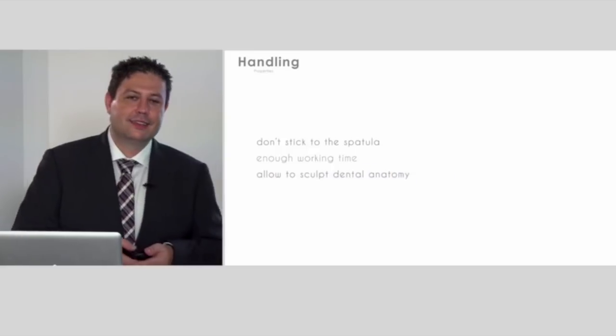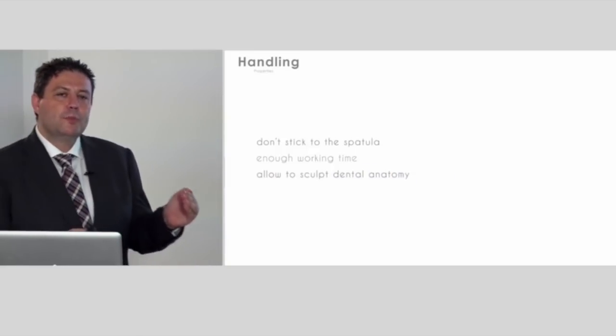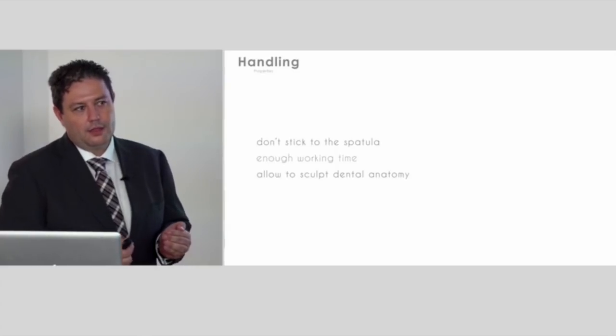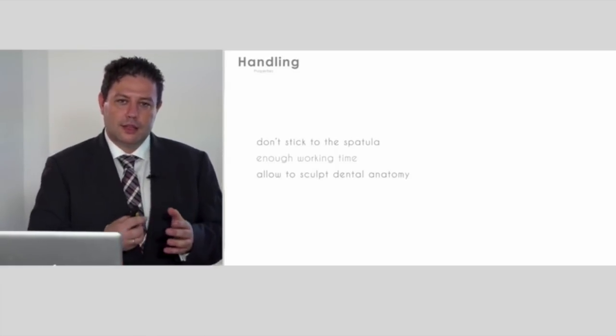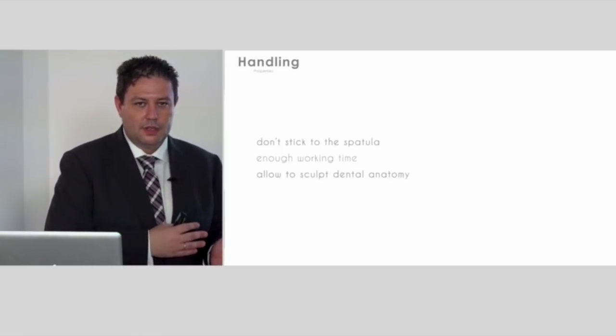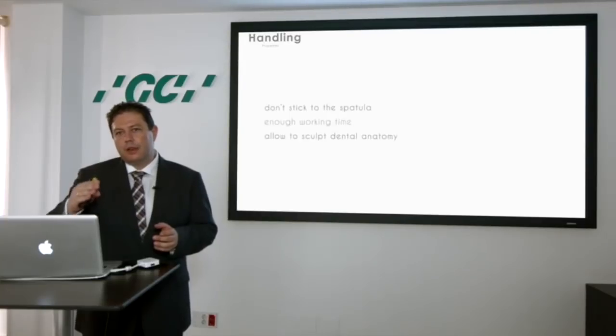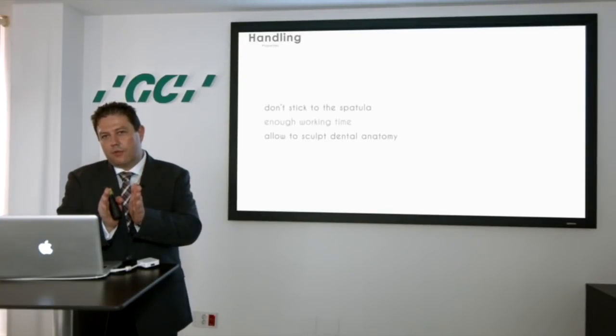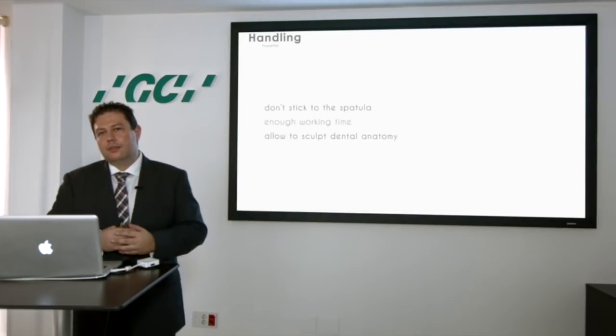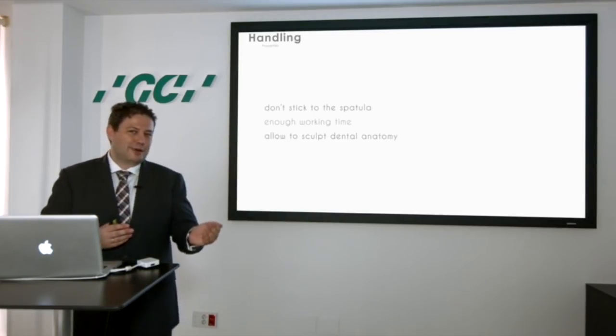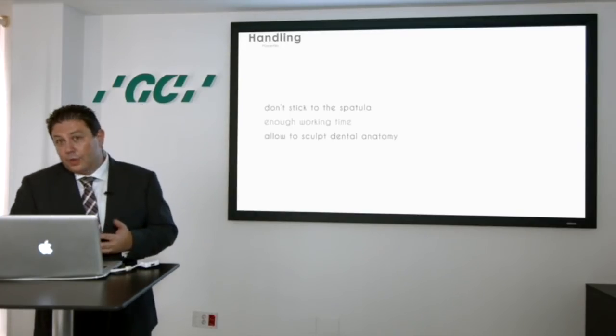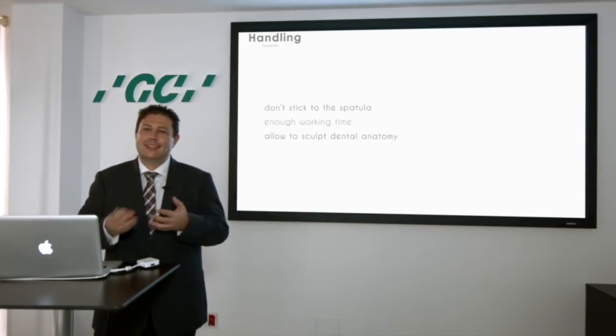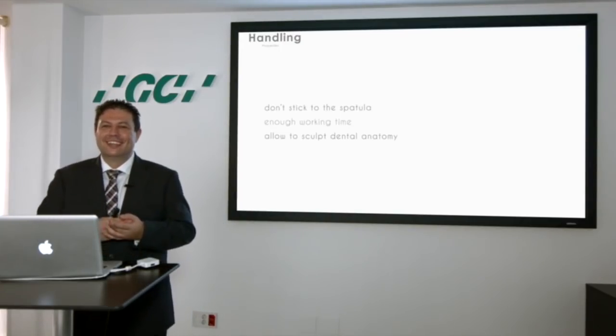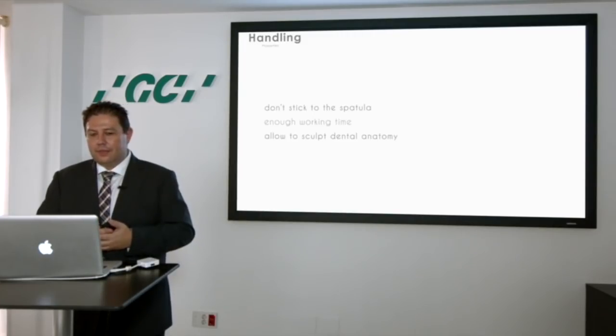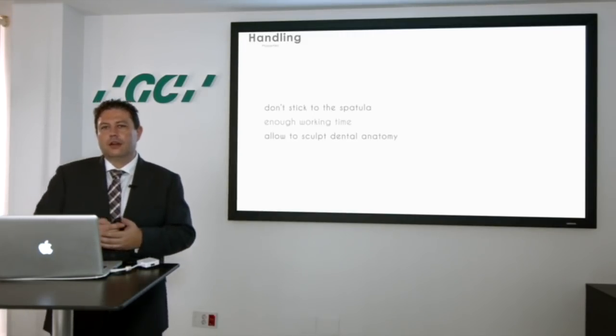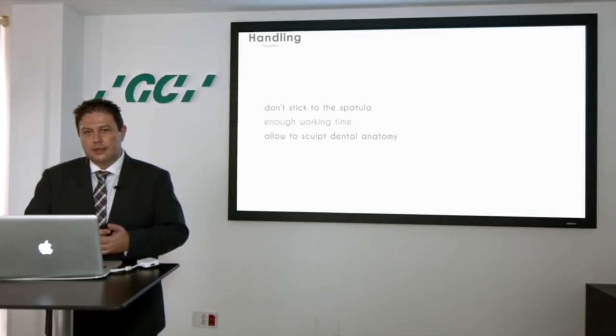And the third thing is that we need a material that allows us to reproduce the dental anatomy, and not have it modified afterwards. That means if you build up a mamelon, you need that mamelon to stay in the form that you made with your spatula, and the best thing is to make it with a material that doesn't stick to the spatula and with light. We can tell the companies, okay, let's change the composition of the material because I want to improve the handling.